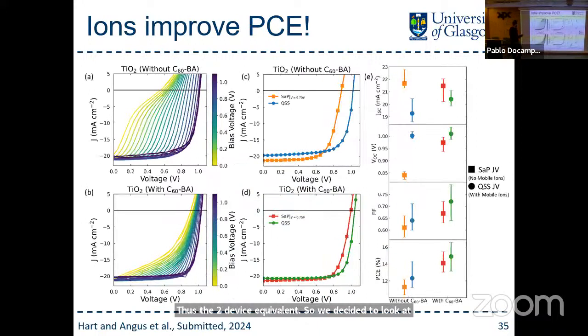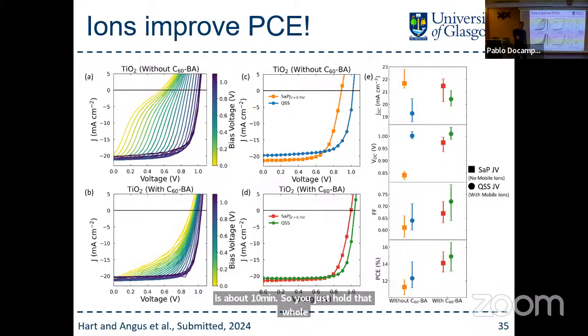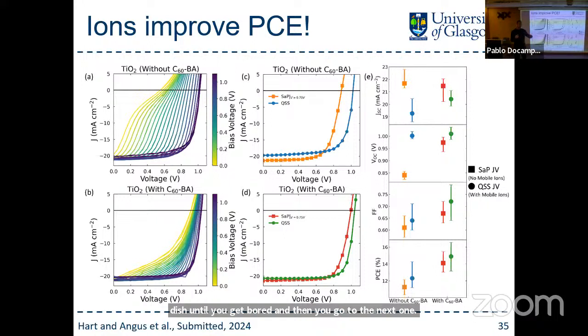So we decided to look at that. We did the measurement, and then we basically did a really slow JV curve. Each of these points in the quasi-steady-state curve is about 10 minutes. So you just hold that voltage until you get bored, and then you move to the next one. Effectively, this allows the ion population to equilibrate, which gives you the JV curve with ions, right? Because that would give you the effect of the ions at each of these voltages. And then we compare that with the pulse JV, where the ions are held constant, uniformly distributed inside the device. So that's the comparison that we're making.